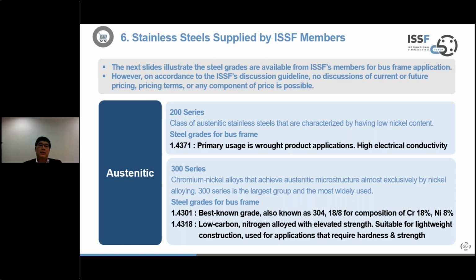200 series is a class of austenitic stainless steels that are characterized by having a low nickel content. So one of the grades that you can use is 1.4371. It has high electrical conductivity. Now, for the 300 series, what is it?